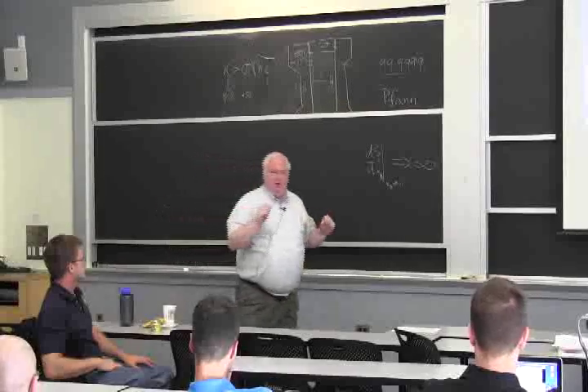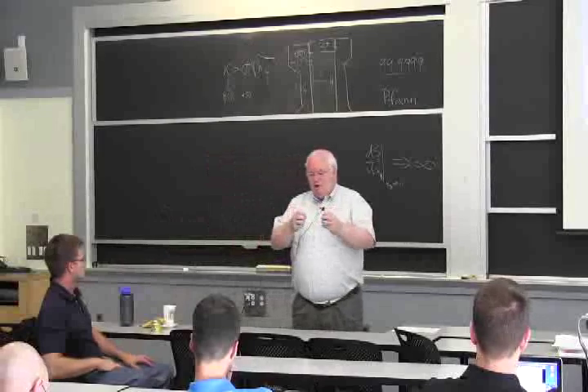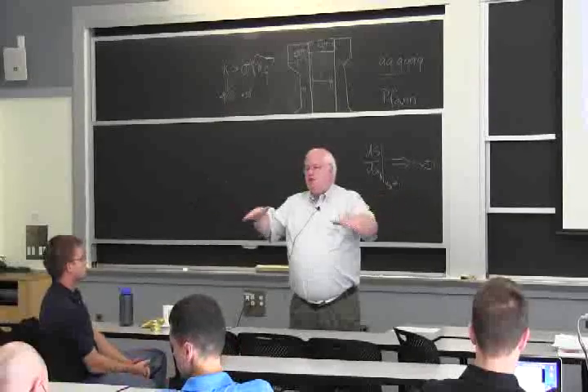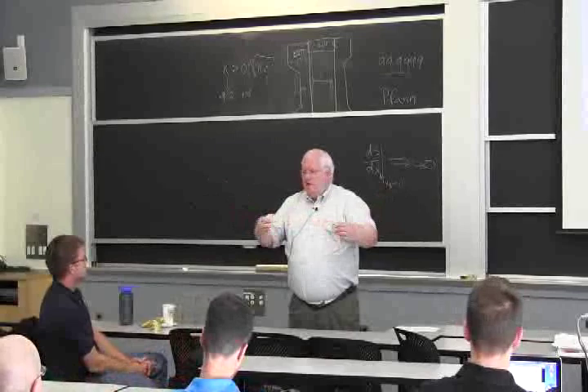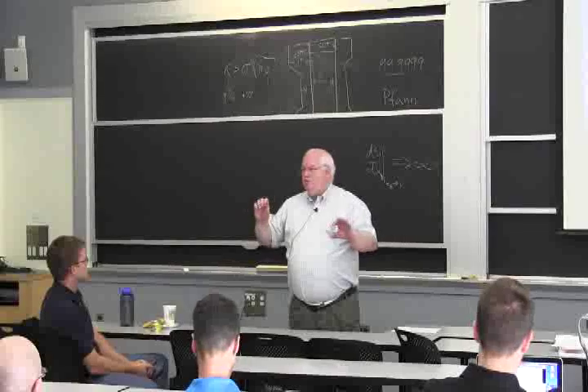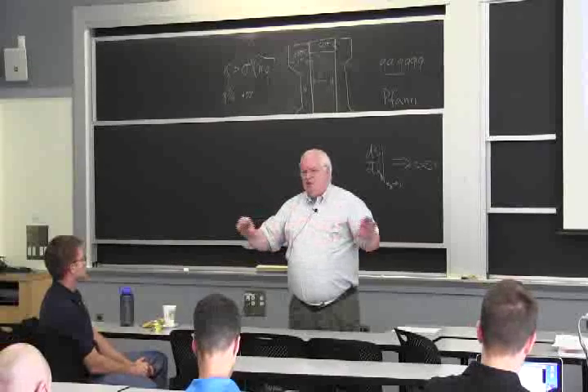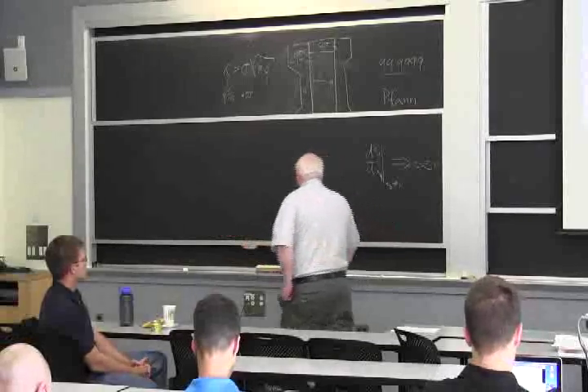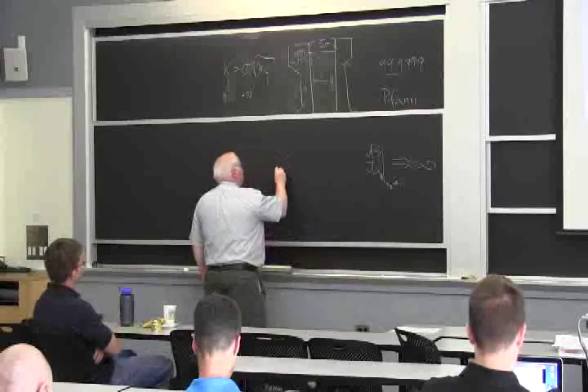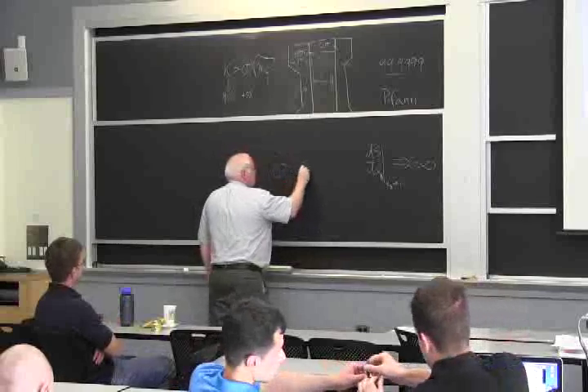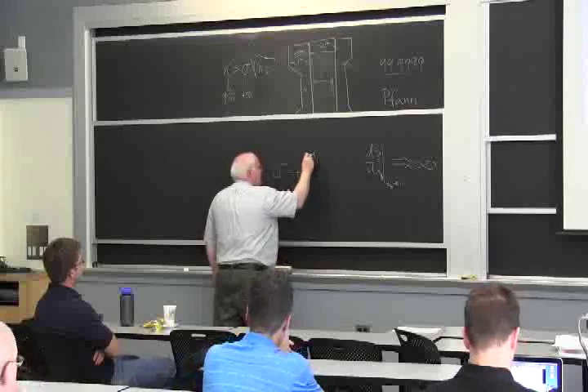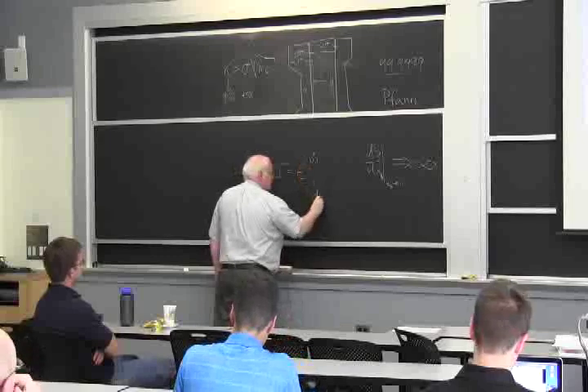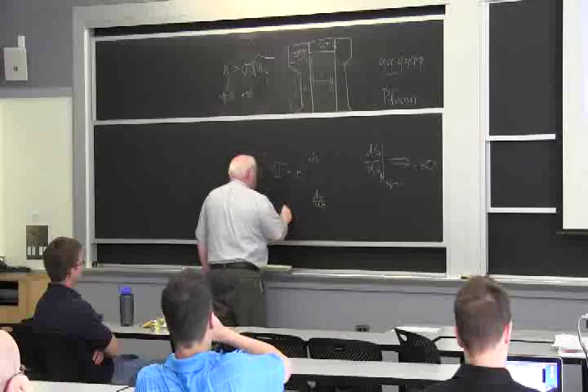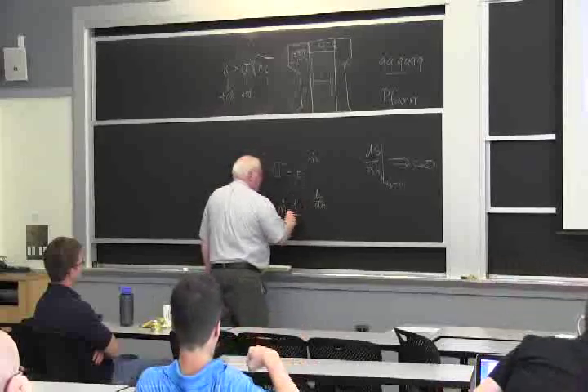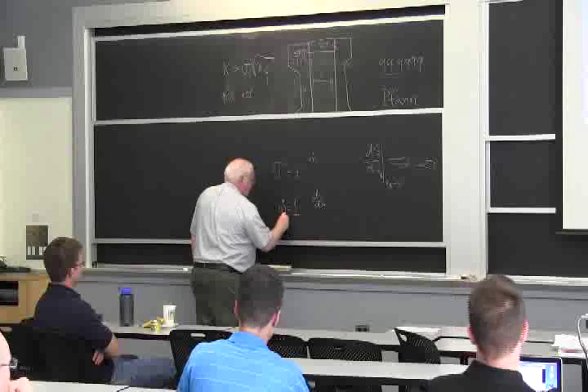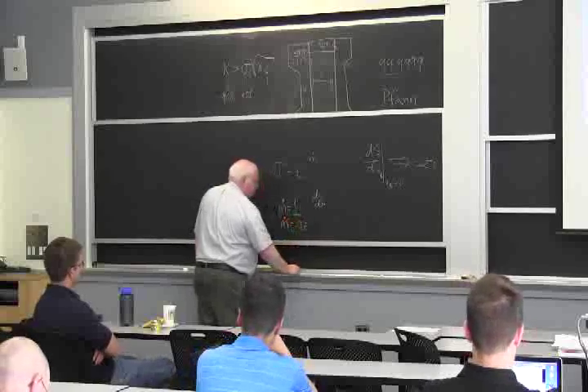Now, a Newtonian fluid is something that doesn't matter if it's different in cross-section. You can stretch it out and it will maintain the same general shape. If it had waves in it to begin with, you can stretch it out and it will keep the same general shape between the peaks and the valleys, okay, as a Newtonian fluid. Basically what we mean in a Newtonian fluid, we mean that if you look at the stress is equal to the strain raised to some strain rate. So this is dε/dt, okay? M is the coefficient exponent. A Newtonian fluid is when m equals 1. For a typical metal, m equals 0.2, okay?